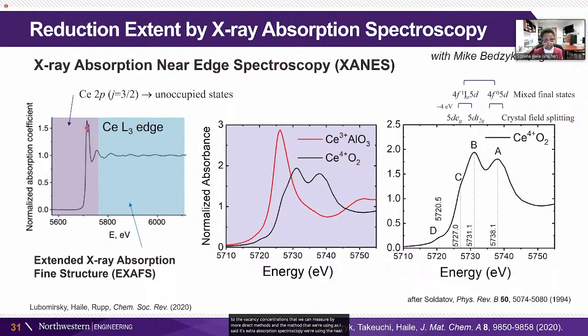We're using the near edge region here, which gives us the cerium oxidation state. The extended region gives us the coordination number. It's much harder to model. With the XANES region, we're really looking at whether we have cerium 3+, which is given by this red spectrum, or we have cerium 4+, which is given by this black spectrum. And I just put this out here because this is an electronic structure conference to say that this is a really, unfortunately, complicated spectrum for the cerium 4+. Not my measurement at all. This was calculated some years back, but it's important for us to be able to understand what this fully oxidized cerium 4+ spectrum looks like so that we can use it to calibrate our own measurements.